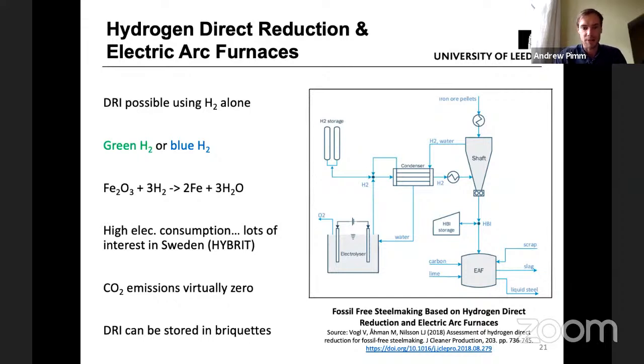So it's a very high electricity consumption, and there's been a lot of interest in it in Sweden, I guess partly because they have a lot of low carbon electricity coming from hydro and nuclear. The CO2 emissions of this route are effectively zero, particularly if you're using green hydrogen produced electrolytically, powered using zero carbon electricity, and you're also using zero carbon electricity to power the electric arc furnace. It's also possible to use blue hydrogen, which is produced using methane, so steam methane reforming, and then capturing the carbon. However, there would be some fugitive emissions from the methane, and some residual emissions from the CO2 capture as well. But it would certainly make a good transition step towards using electrolysis to produce green hydrogen.